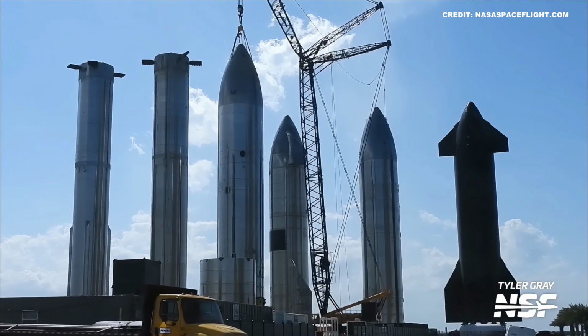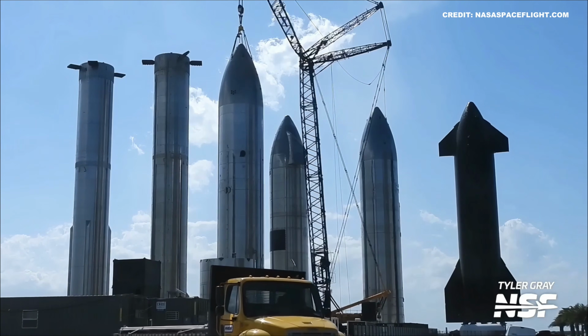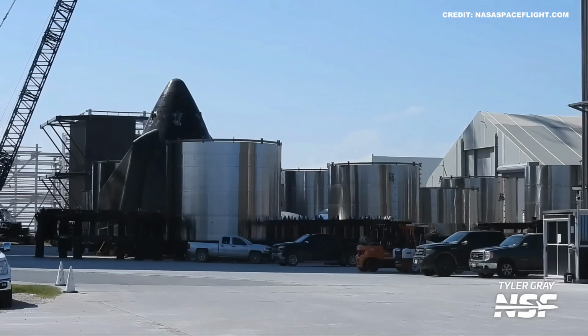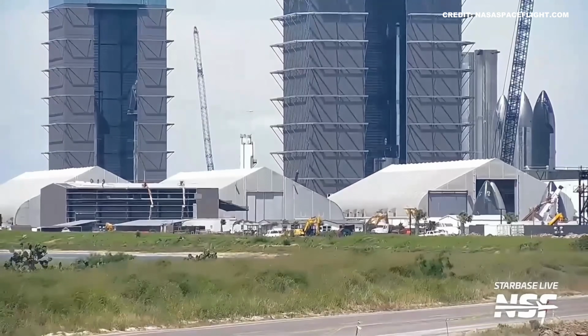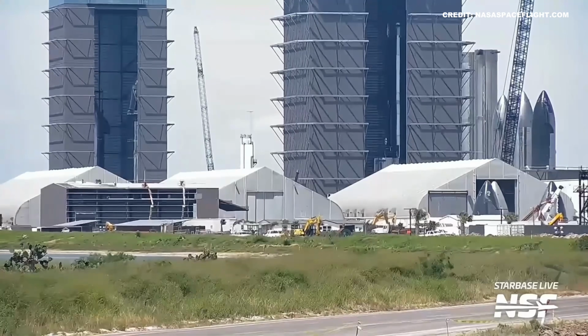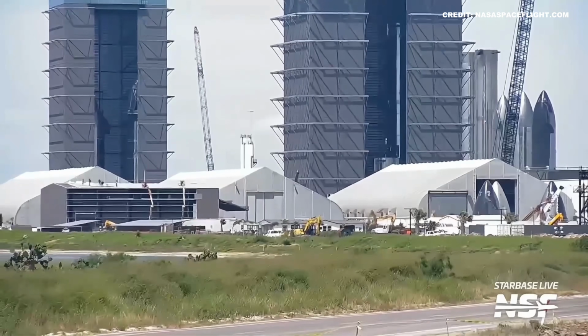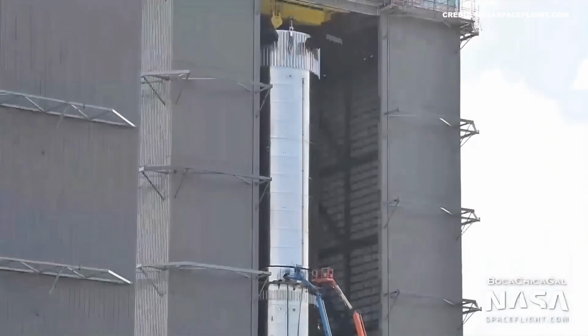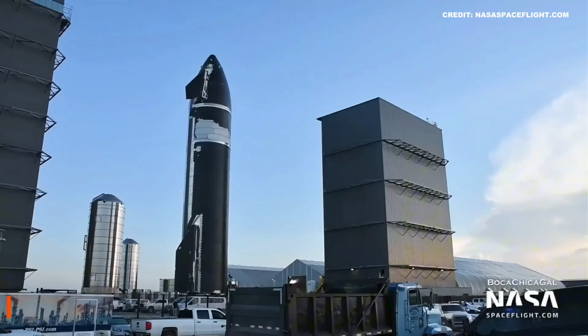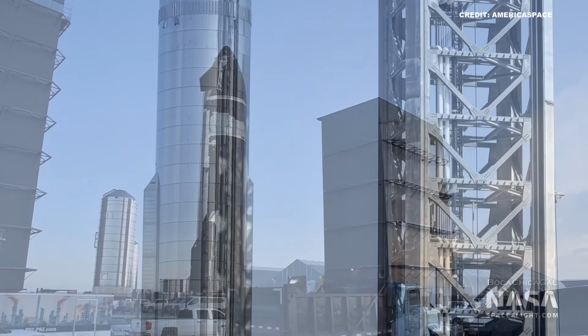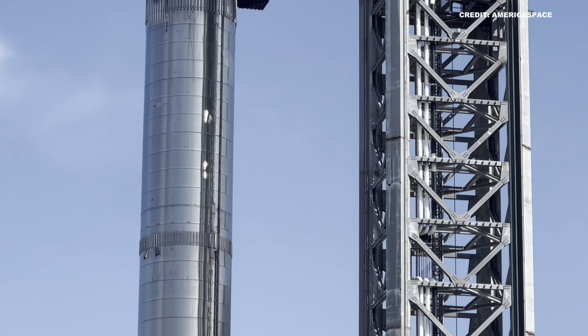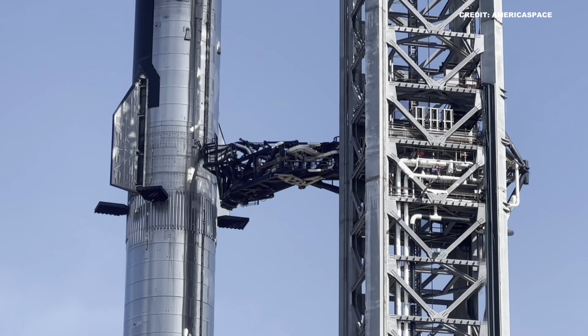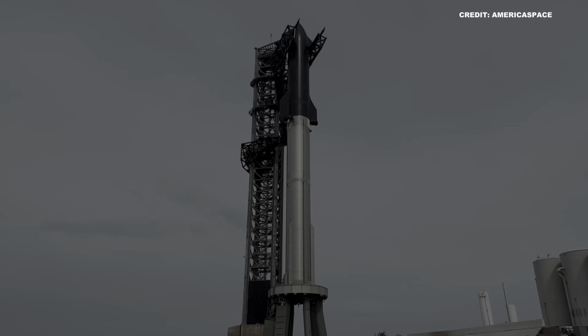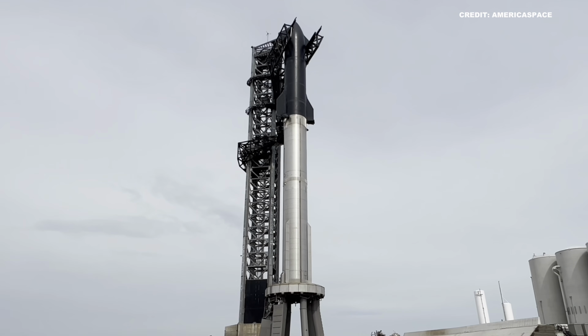Keeping a 9-meter diameter cylinder perfectly circular is straightforward inside a closed factory. But at Starbase in South Texas, high winds averaging 25 to 40 kilometers per hour, though on rough days, field crews report gusts pushing well past that, exert massive lateral pressure on the exposed steel. With a wall thickness of only 4 millimeters, each ring behaves like a giant flexible sheet. The wind force easily warps the cylinder's shape, causing deviations of up to 50 millimeters from a perfect circle. Attempting to weld under these conditions is impossible.